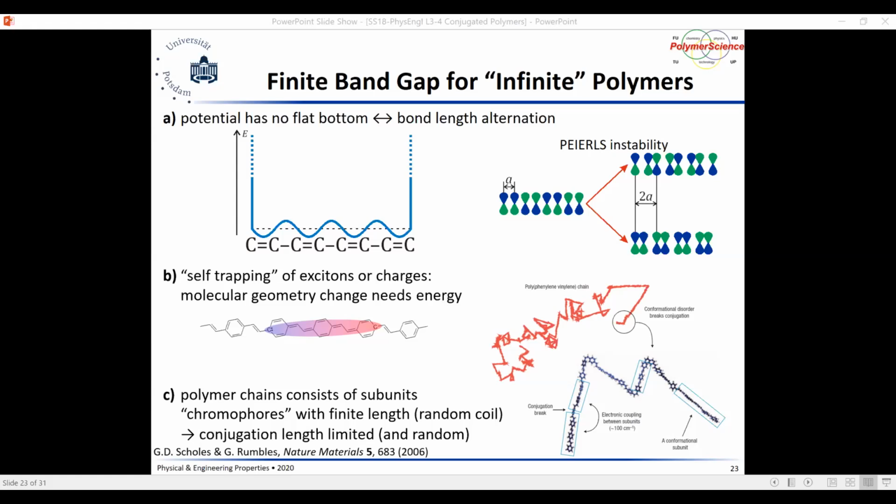The change in exciton size and excited state character takes place over tens of femtoseconds, and this requires nuclear reorganization. If you do spectroscopy, this will show up as large Stokes shifts between the absorption and emission.